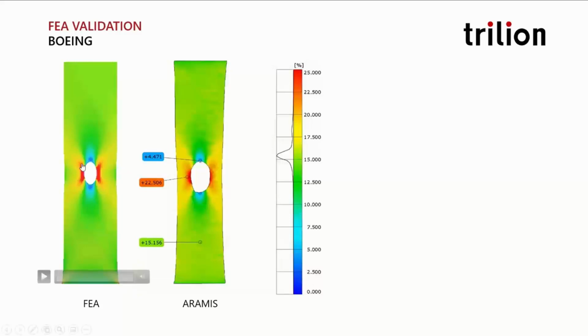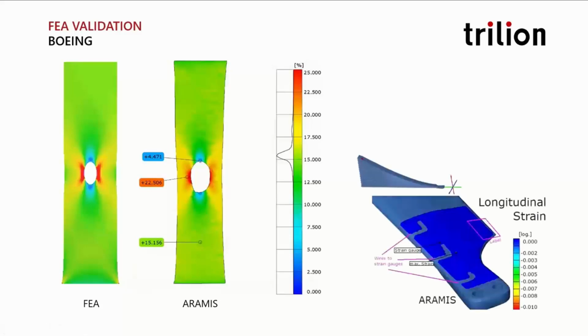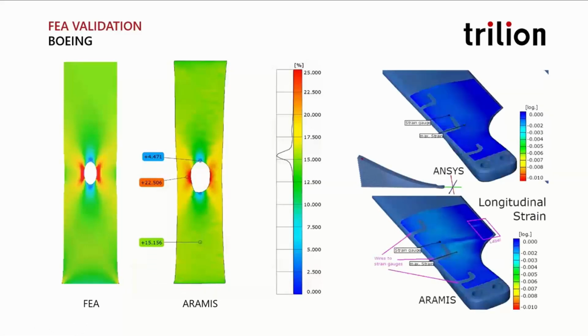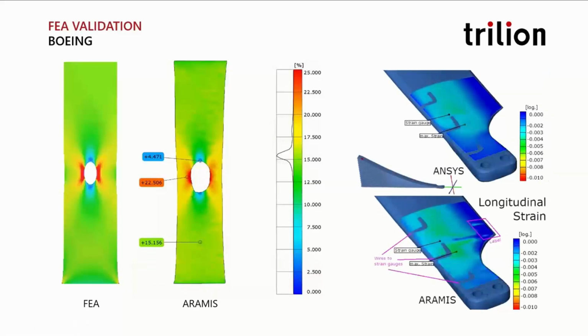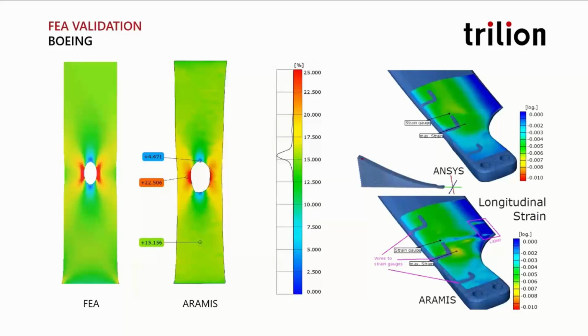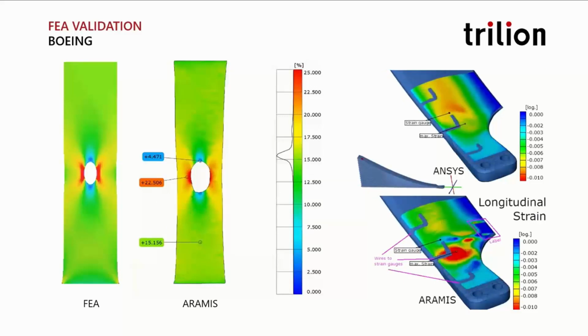In simple homogeneous materials, you're seeing good equal response in the ARAMIS result versus the finite element model. The local variations here are true local variations in the material. So you're seeing right down into the material structure. But when you get into real components, the model versus the reality is sometimes very much different than anticipated. And you can see in this case, a strain gauge expecting to see a high strain concentration right there was not seeing anything, caused by structural defects in the material.